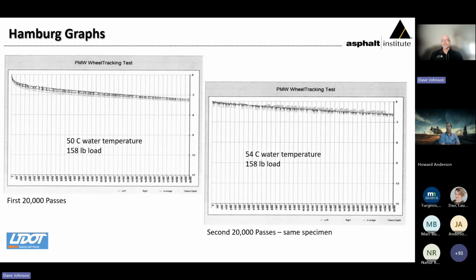For those who've seen Hamburg graphs, these are the two 20,000 passes. Notice how linear these graphs are. There is certainly no stripping inflection point. Very rich, low air void mixes are not likely to have issues with stripping, and that is not a surprise that we don't see that stripping inflection point, but it is an extremely stable mix under the Hamburg.